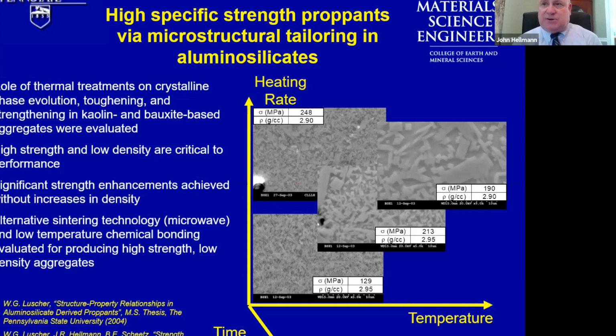These were commercial materials where we expanded the range of sintering temperatures, sintering times, and interestingly, the heating rate to get to the sintering temperatures. The heating rate is an important characteristic because these materials are sintered in large rotary kilns, much like a cement clinker manufacturing process. And therefore, not only the temperature that you go to, but the residence time of the material during the sintering process has an impact on the amount of hydrocarbons that you use as the fuel to heat the process, as well as the CO2 that's generated during the process.